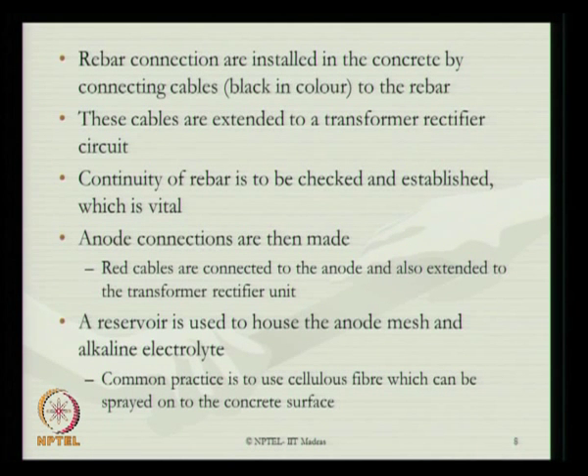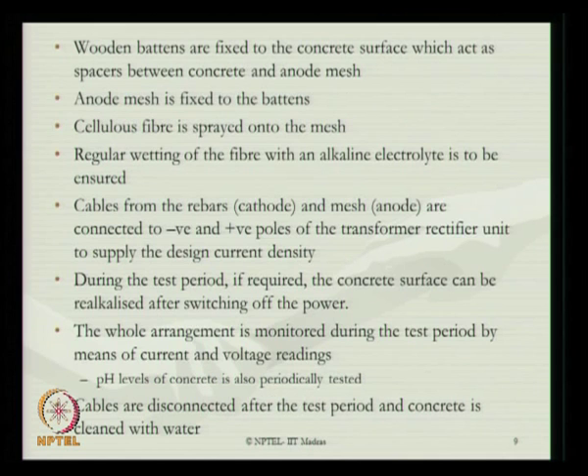Now a reservoir is used to house the anode mesh and the alkaline electrolyte. The common practice is to use cellulose fiber, which can be sprayed on the concrete surface, which will act as an electrolyte medium. Wooden battens are then fixed to the concrete surface, which act as spacers between the concrete and the anode mesh. Anode mesh is then fixed to these battens. The cellulose fiber is sprayed on the mesh. Regular wetting of the fiber can also be done, as an alkaline electrolyte is to be ensured.